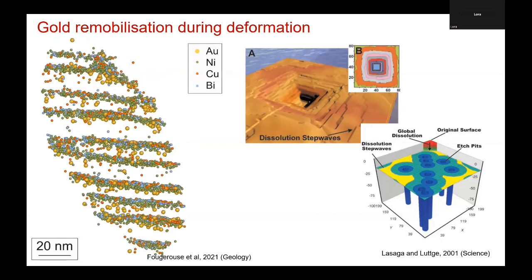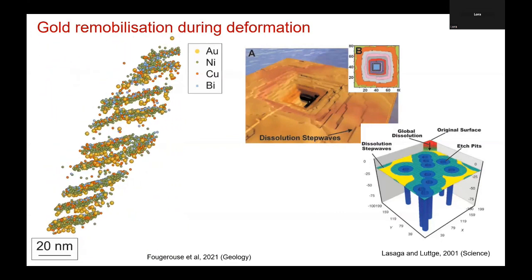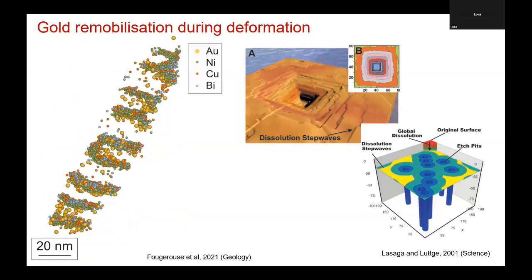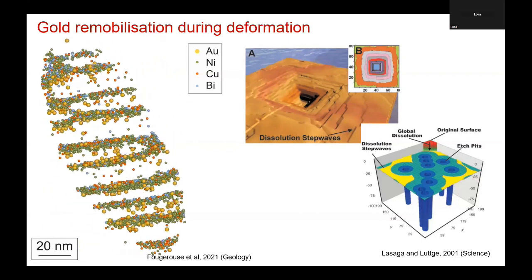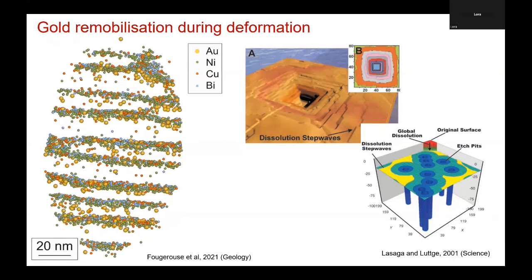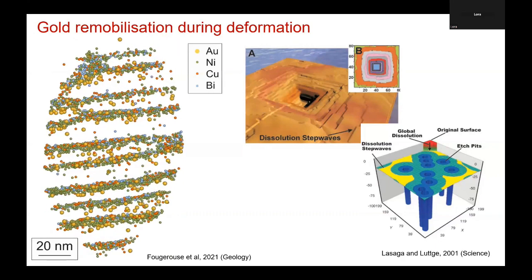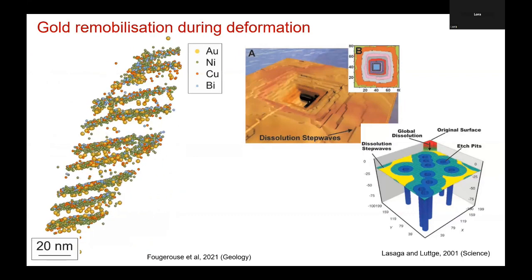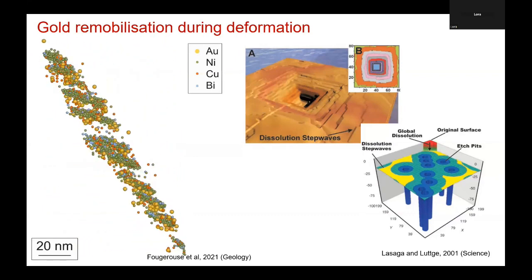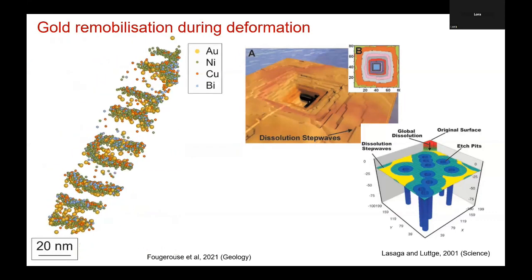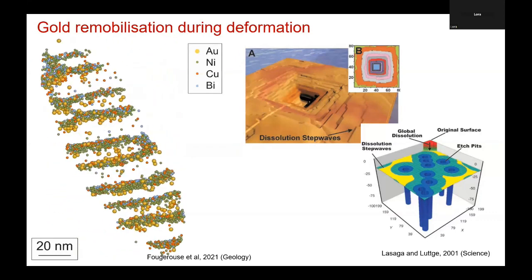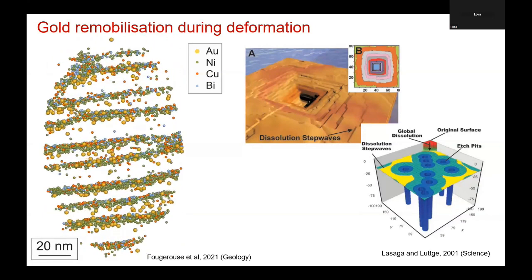And that's great. I don't have anything against that. But when we think about things like in situ mining or mining of very low grade rocks, some selective leaching like this may actually be quite beneficial, especially if our pyrites are quite deformed. There's lots of these dislocations around, which have collected a lot of the gold during the deformation. We could potentially find a way to extract that gold quite cheaply.